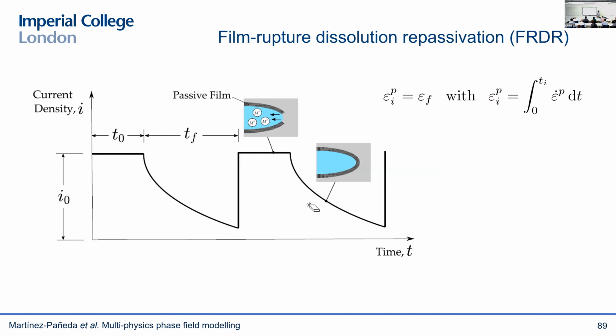And there's another important effect for mechanics. Very often, we have a passivation film that protects the metal from corroding. This is what happens, for example, in stainless steel. And therefore, your metal will not corrode unless you have mechanical fields that are large enough to rupture that passivation film, and then you get this kind of localized pitting and stress corrosion cracking. So at the end, it's a competition between, I would say, passivation kinetics and straining kinetics.